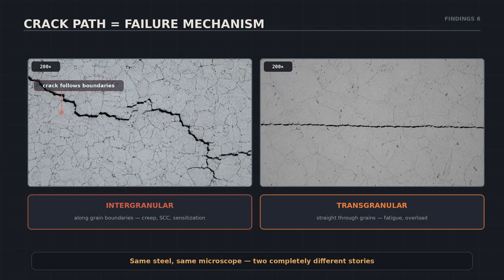Cracks tell their story by the path they take. On the left, intergranular, the crack weaves along the grain boundaries, avoiding the grains themselves. That's the signature of creep, stress corrosion, or sensitization-assisted attack. On the right, transgranular, the crack cuts straight through the grains as if they weren't there. That's fatigue, or overload. Same steel, same microscope, completely different mechanisms, and completely different responses.